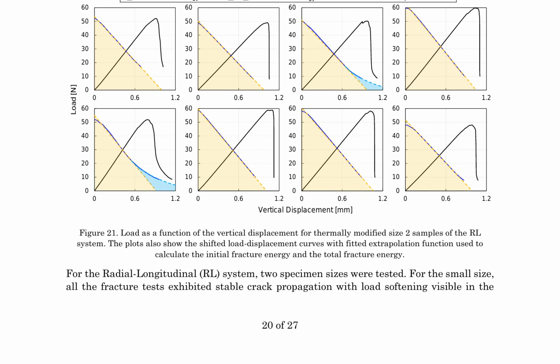The study highlights the importance of understanding the influence of thermal modification on the fracture behavior of wood, particularly in terms of its grain orientation and damage mechanisms. The results suggest that the TL system exhibits more extensive damage and different fracture mechanisms compared to the RL system. This research contributes to the development of new strategies for improving the fracture resistance of wood through thermal modification.